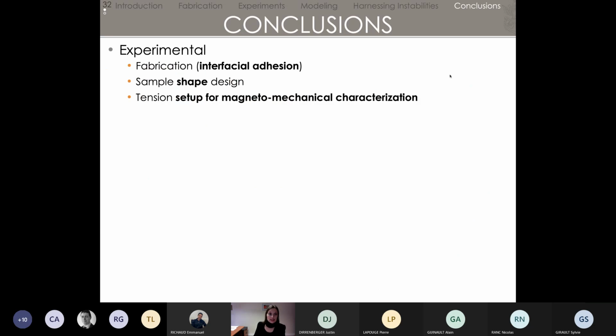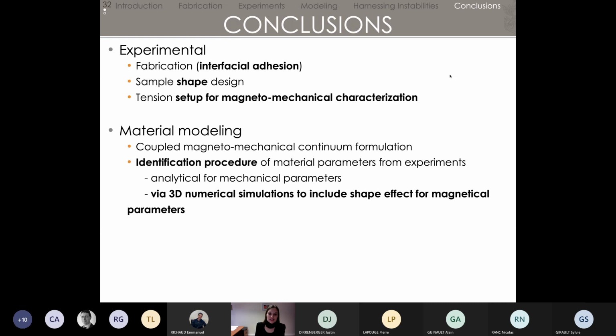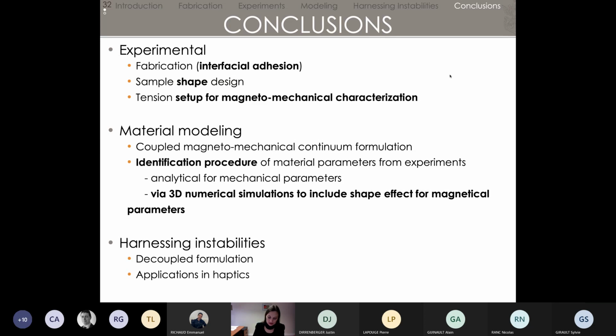So to conclude, experimentally, we figured out fabrication. We did some sample shape design and proposed a setup with the idea of doing some material parameter identification. This can be done analytically if you're just looking at the mechanics, and not at all if you're trying to look at the magnetic parameters. You will have to go through 3D numerical simulations, which is not very easy and fast. And in the end, instabilities, which we thought was a big problem at the beginning, tend to be quite interesting when you can harness them properly.